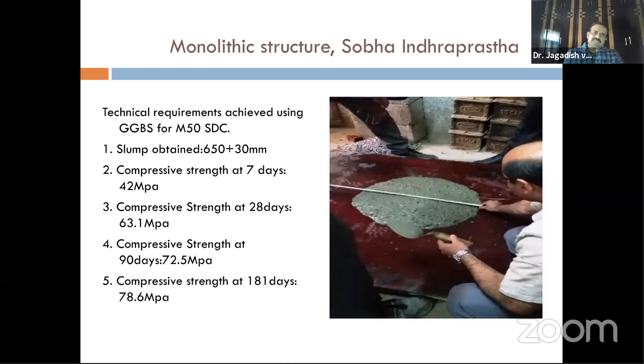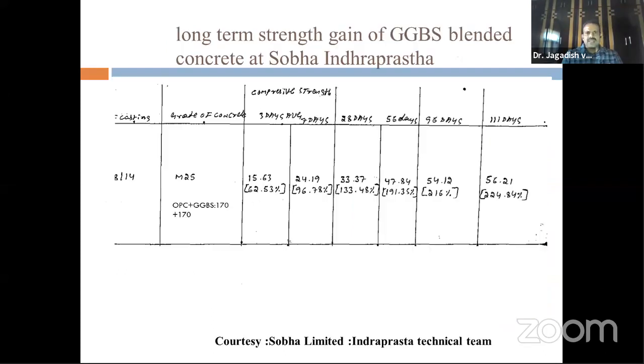So GGBS, they've used it in one of the structures, that is Sobha Indhraprastha. It's a monolithic structure in Bangalore, wherein they've used the M50 grade of SCC, wherein GGBS is used. The slump they got is around 650 plus or minus 30, and then compressive strength is 42 at 7 days, in 28 days they got 63, and at 90 days they have almost got 72 MPa. Even 181 days is 78 MPa with GGBS. This is an example wherein GGBS can be used in these special concretes.